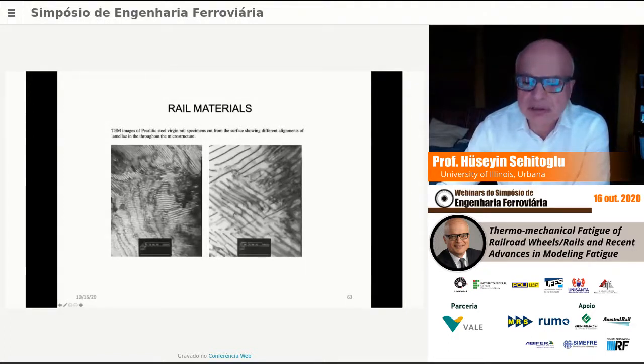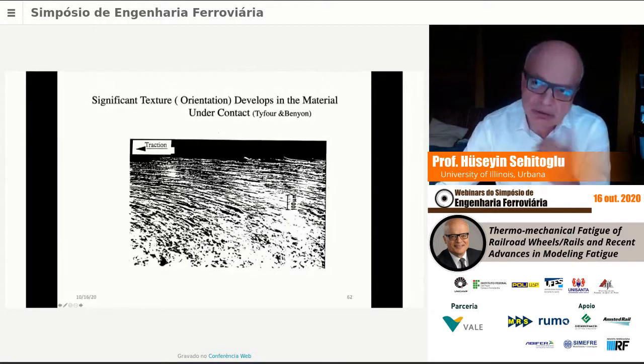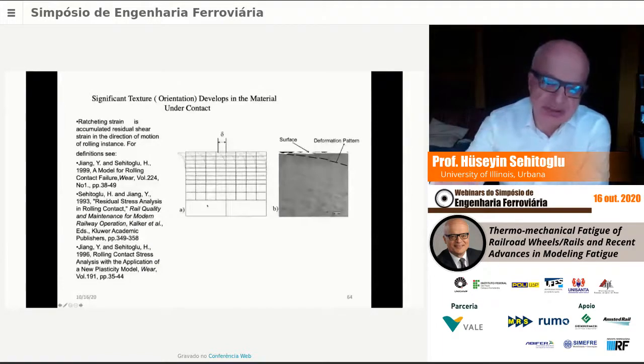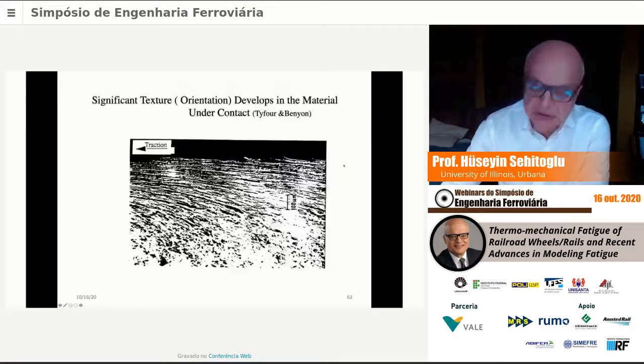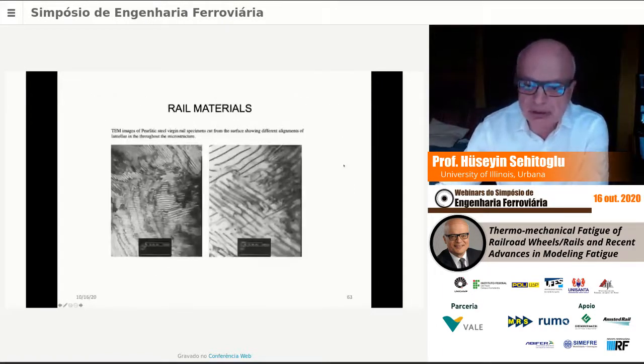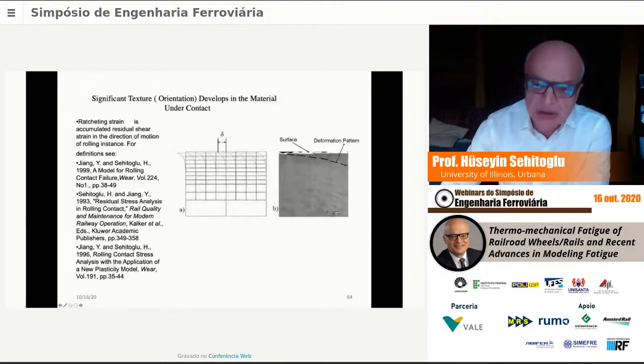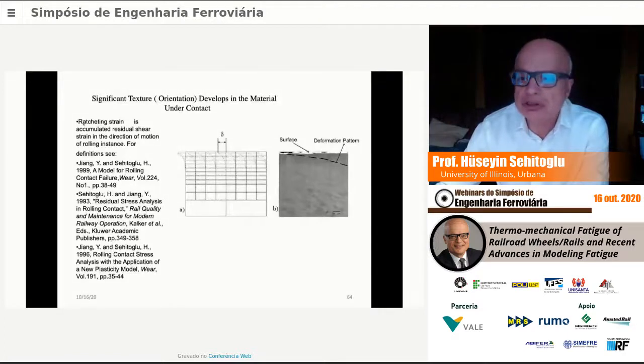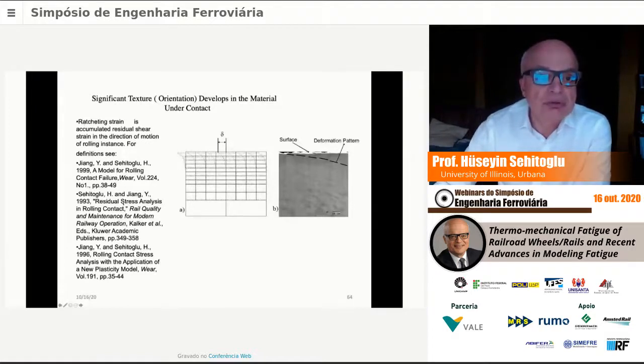These are TEM pictures. So the pearlite spacing is a little bit finer here compared to the previous pictures I showed, which were scanning microscope. These are transmission microscope pictures. This is 200 nanometer. So the issue is, of course, I'm sorry about that, deformation of the surface. And we define the ratcheting strain as the accumulated residual shear strain in the direction of motion of rolling. These are the papers we have on this.